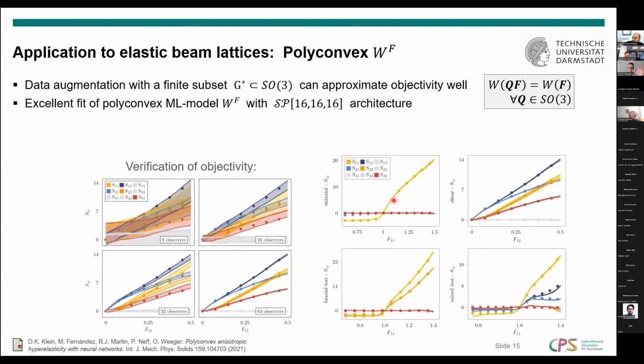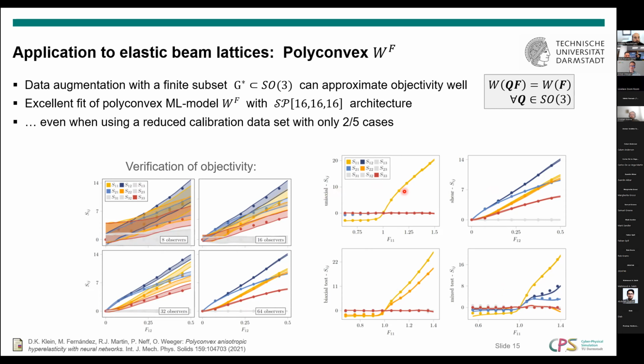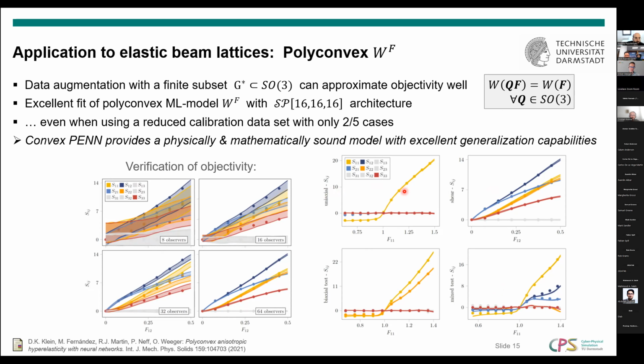So here, basically, you see uniaxial and shear cases, which were part of the training data set. And here, this biaxial test and the mixed test case, which were not part of the training set. And we have a very good prediction of the stress-strain behavior in all cases. And we get this even when we use only 2 cases, such as uniaxial tension and shear, which are very simple training cases, to train the model, and we are still able to generalize the prediction to any other kind of deformation. So it's this convexity that we added here to the physics-enhanced neural network that gives us a physically and mathematically sound model, which is highly accurate and has excellent generalization capabilities.